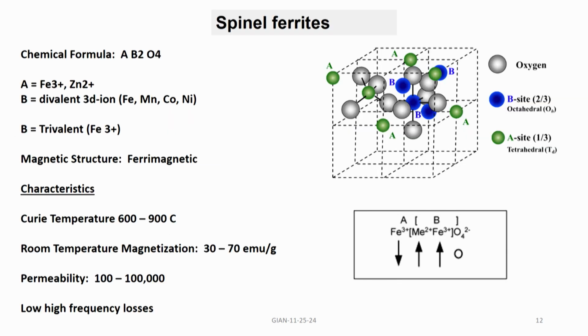Okay, spinel ferrites, it's an oxide containing iron 3 plus. In all of them, there is trivalent iron. There is also a divalent ion. It can be either magnetic or non-magnetic. Now, just to give you a flavor, the spinel ferrite has a cubic structure. The lattice constant is around 8 angstrom. The density is around 5.4.